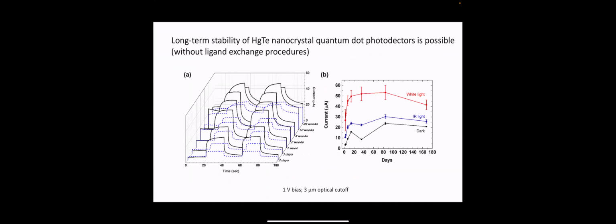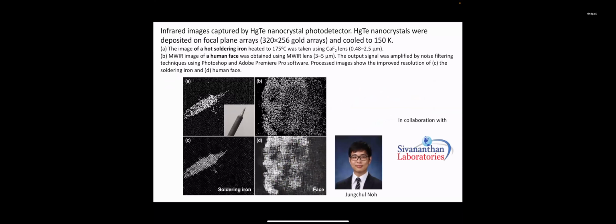So under certain conditions, we actually don't have to do the ligand exchange. And we've had devices that have been stable for months. Here we're looking at 6 months, but those devices now are over a year old. And so here what you see is mostly that slow on response and off response. That's an issue, but they're very stable.